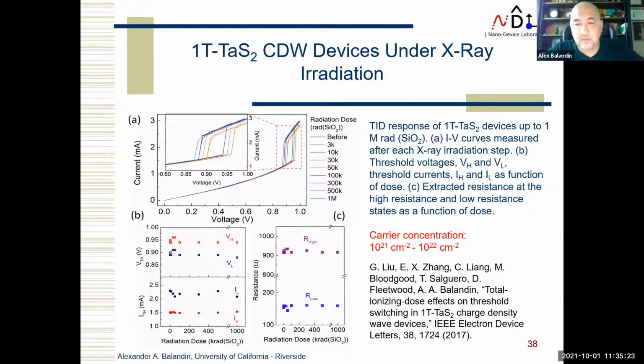Now, of course, when we did this device, people asked, what's good about this device? How can it compete? One of the possible advantages is radiation hardness. If we are going to move to Mars anytime soon, we need electronics which is radiation hard against X-rays and protons. Conventional semiconductor devices are not radiation hard because damage created by X-rays or protons gives you trapping centers, and trapping centers take electrons away. You increase noise, and of course also charge accumulation at the interface can shift the threshold fields, etc.